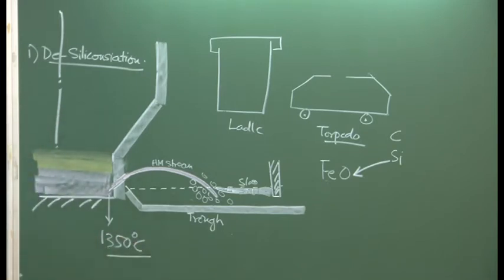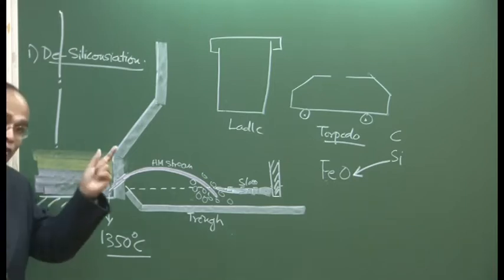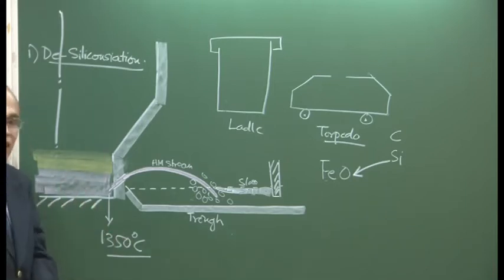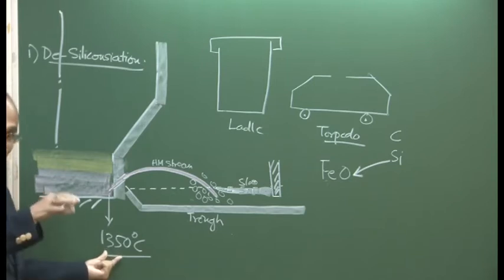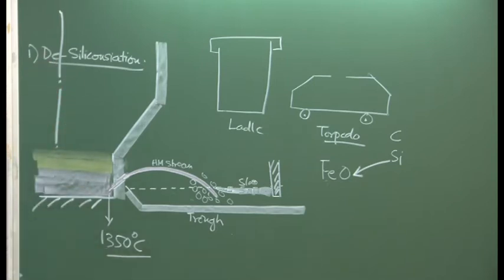we cannot go to 1450 or 1475 degree centigrade, as I have indicated. So, the blast furnace hot metal will be tapped under Indian conditions at about 1350, otherwise there is a danger of getting too much silicon in the hot metal itself. But in foreign blast furnaces, where the silica content of the charge is smaller, one can go to 1450 or a higher blast furnace temperature.